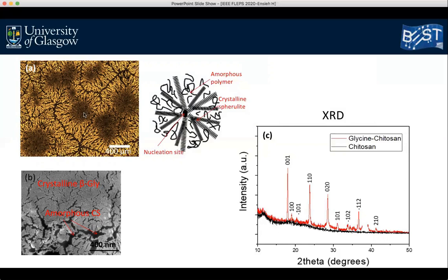And each of these spherulites of glycine is like a single crystal with a nucleus in the center, and the fibrils of the spherulite radiate out as shown schematically in this figure. And here an SEM image showing that the glycine crystals are embedded in the amorphous region of chitosan very well. So the polymorphic phase of the glycine crystal embedded in chitosan was determined by XRD. This XRD pattern, this red pattern, confirmed the formation of beta-phase glycine crystal inside the chitosan. And this black pattern is just pure chitosan that shows no sharp peak. It has just a very broad peak that is due to the amorphous structure of chitosan.